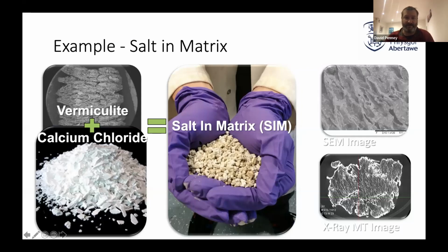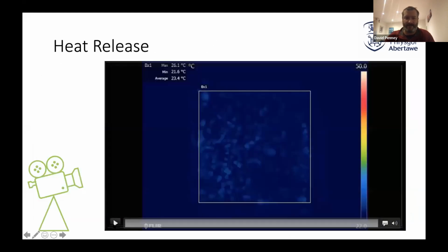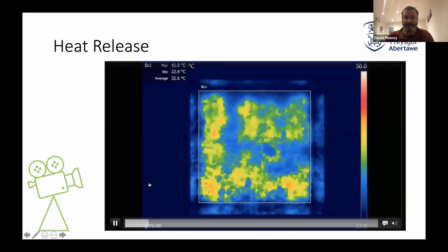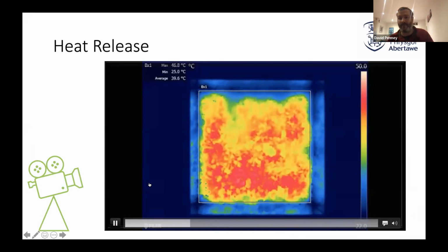It's not dissimilar at all, a very light ceramic material, full of pores, and then impregnating that with a salt, calcium chloride. You can see that on the bottom here. So you get this salt impregnated into this matrix, and you can see an X-ray image of it there. And then what happens is that salt, when it gets wet, gives out heat.